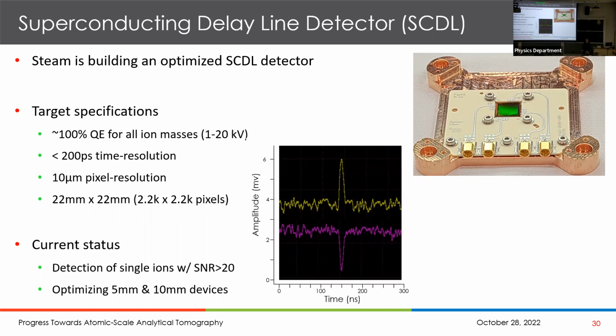So you've tried very hard to avoid multiple hits or multiple evaporation events. And so the bottom line is the best state-of-the-art atom probes today operate with a very low or very sparse evaporation probability. One pulse in 100 pulses produces an evaporation event in a typical operation. So if we can resolve both events or even 10 events per pulse, then we can run that up to, say, not 0.01 atoms per pulse, but we can run it 1 or 10. This is 1,000 times higher data collection rate.